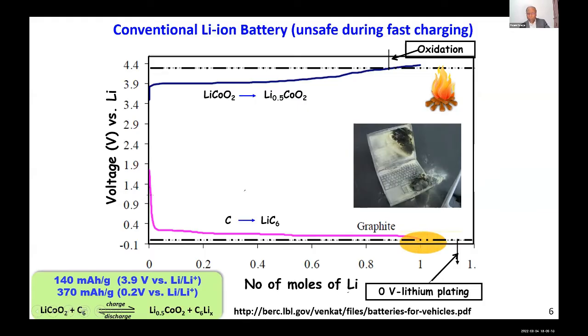When you are removing lithium, you are also inserting this lithium into the graphite. Simultaneously, it is happening. So insertion into the graphite happens at 0.2 volt versus 0 volt, which is the lithium. So you can see here the insertion potential is very low, closer to the lithium metal reference potential. So if you do fast charging, by chance, what happens is you inherently end up with so-called metal deposition on graphite. And this metal deposition happens in the form of dendrite growth.